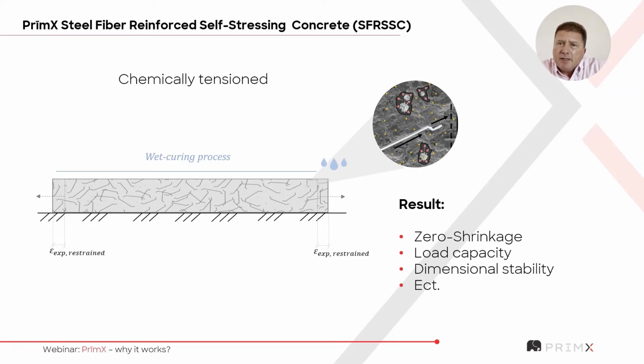A shrinkage compensating admixture will actually work by a delayed process. As the concrete itself starts the shrink wrapping process, as the cement mortar does its bit, it's reducing in volume, shrinking, pulling everything tight. So we have a delayed reaction and the formation of expanding minerals, ettringite particularly, which actually starts to force the concrete apart at a microscopic level.